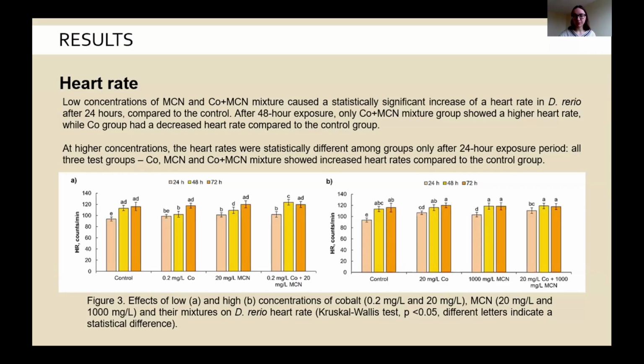We saw similar results using higher concentrations, so the graph on the right. Here, the heart rates were statistically different among groups only after the 24-hour exposure period. So all 3 exposure groups, cobalt, MCN, and the cobalt plus MCN mixture, showed increased heart rates compared to the control group. And as I mentioned, after 48 hours and 72 hours, there were no more statistical differences here.